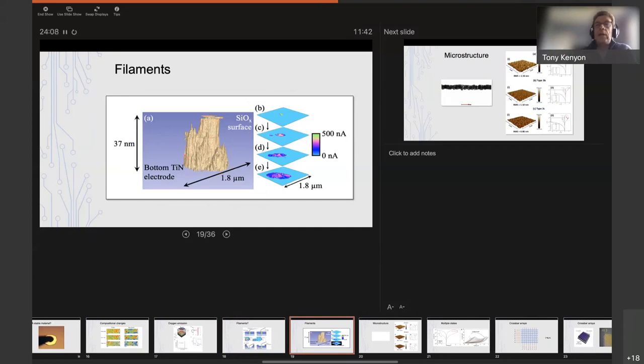But also interestingly, there's internal structure to this. It's not just a single pathway, but there's a lot of interesting internal structure. Can you see these sorts of columns that seem to be growing out of the bottom electrode towards the top electrode? So we're seeing evidence of the conductive filament and also some internal structure in the oxide, which I'll come back to in a second.